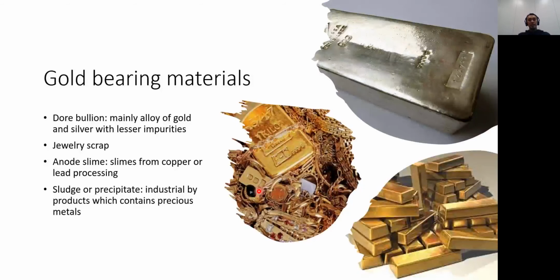And then, yes, this is a little bit in touch with the gold bearing materials. So for the gold bearing materials, mainly the precious metal refinery processes doré bullion, which is produced by gold mining, and then they also receive jewelry scrap and anode slimes. So the slimes from copper electrorefining also contain a high amount of gold, can be 3 to 5% or even higher, depending on the copper concentrate, and slags or precipitates of industrial waste that contain precious metals. So these kinds of materials can be processed in a precious metal refinery.